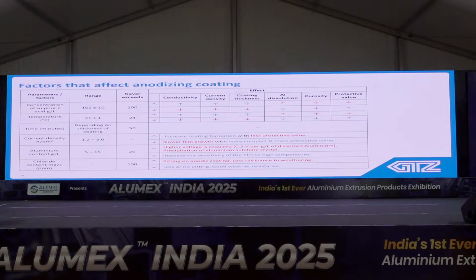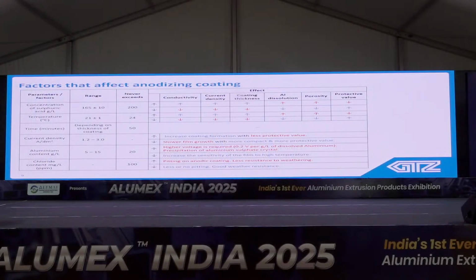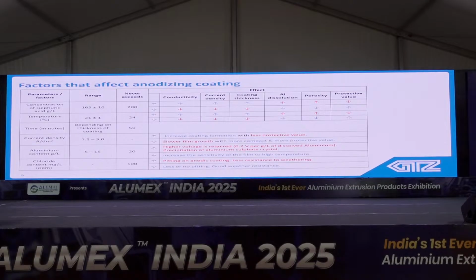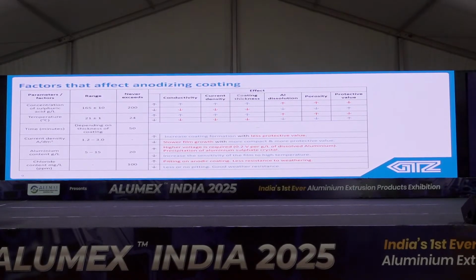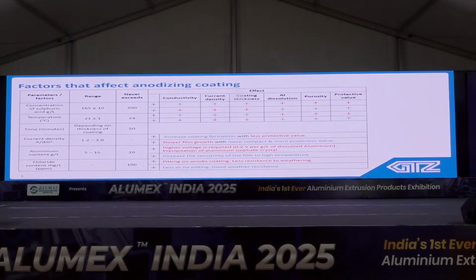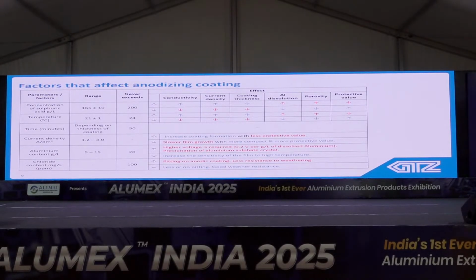Time depends on thickness, but there are two rules of thumb for time measurement. One is the 3.12 rule: time required in minutes equals the desired micron thickness times 3.12 divided by the current density in amperes per dm square. Another rule: time required in minutes to get the desired mils of coating, where one mil is 25.4 micron, is mils times 720 divided by the current density in amperes per square foot. So the current density is in the range 1.2 to 3. If it is slower, then the film growth will be less and the time will be more. So this is the optimum range.